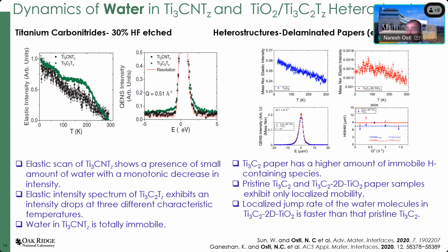Now we move to the different MXene, which is titanium carbonitride MXene, and compare its water diffusivity with that of the pristine MXene. Both MXenes are synthesized using 30% hydrofluoric acid. If you see the elastic intensity profile for the carbonitride, there is a monotonic decrease in the intensity, indicating that there is very little water, if any. But in the pristine MXene, you can see multiple steps. It means that there is water confined at different regimes, and